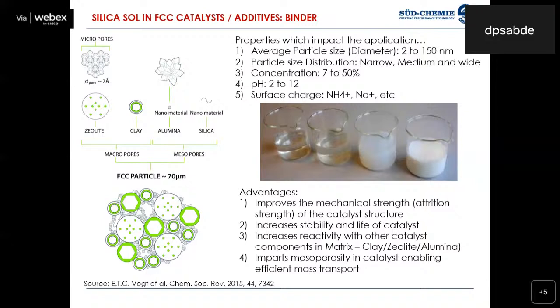Also, silica, if you look at the surface, has a lot of hydroxyl groups, and they have very good binding efficiency with the other matrix components of the catalyst, especially the clay, the zeolite, or alumina. So silica plays a very important role in binding the complete matrix and giving the desired properties to the catalyst particle. In addition, silica also imparts mesoporosity. Basically, that is helpful in efficient mass transport, because there is a wide range of hydrocarbons which are part of the FCC.